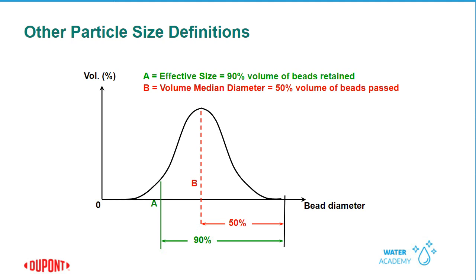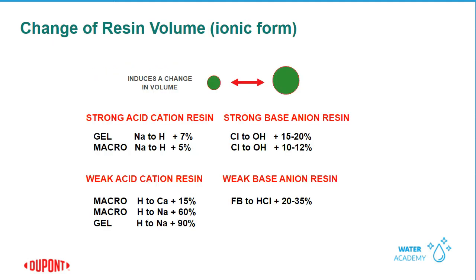The change in resin volume with ionic form. This is a property of the ion exchange resins that you don't want to take you by surprise. It is commonly listed on our product data sheet as % expansion or % swell. This is a property of the resin that anyone who is either purchasing resins for use or designing ion exchange systems should be aware of. In some cases, the expansion can be quite large, such as in a weak acid cation resin. You can get an expansion of 60 to 90% depending on what type of resin you're using and how you're using the resin. Or it could be quite small, like in a strong acid cation resin going from the sodium to hydrogen form, which is about a 7% expansion. So this definitely is a property to be aware of, and it's an important one.